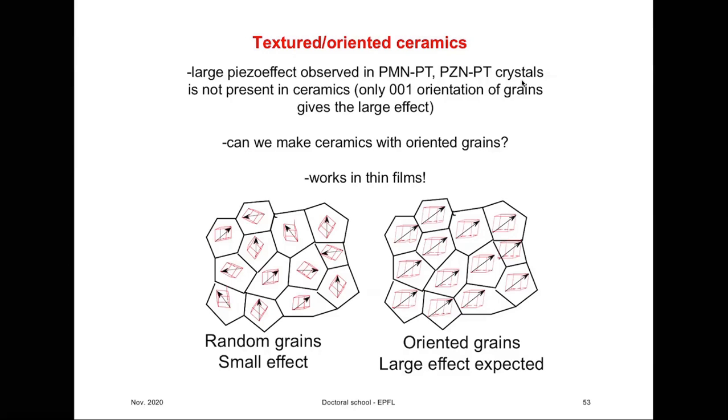You remember the case of zinc oxide that I showed you at the beginning. Zinc oxide tends to grow in these columnar shapes. It's a pyroelectric material, but not ferroelectric. However, in these columnar thin films, it often gives net polar response and therefore piezoelectric effect.